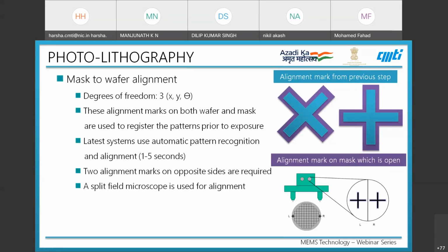These alignment marks on both wafer and mask are used for registration of the patterns prior to exposure, and this can be done in both manual and automatic modes. Two alignment marks on opposite sides are required, as shown in the image at the bottom, which we can recognize through a split field microscope in order to perform the alignment.